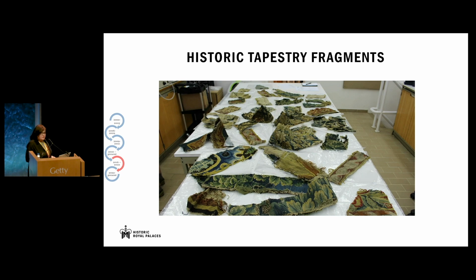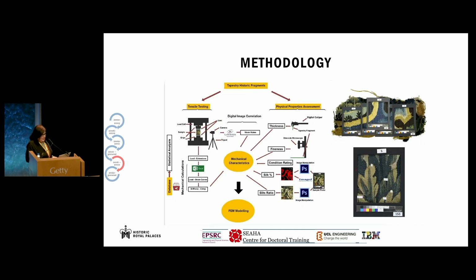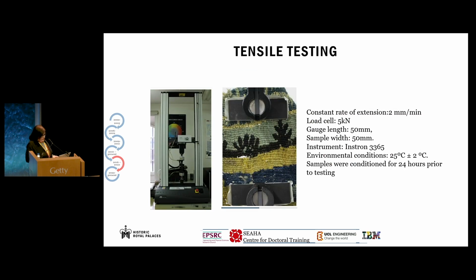So the 10 fragments Philippa used in her research were selected from the Historic Tapestry Archive we're fortunate to have in the HRP's Heritage Science Lab. Pedro, our next PhD student, also selected 33 samples from this archive for his research. And he performed a range of techniques to record their physical properties and also deployed tensile testing with DIC to measure their mechanical properties. And here you can see the tensile testing setup on the left, and on the right experimental parameters. During tensile testing, a camera was recording a set of pictures at each 1 millimeter extension, and these images were then used for the DIC.